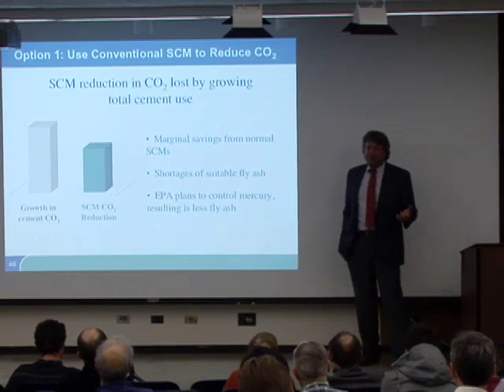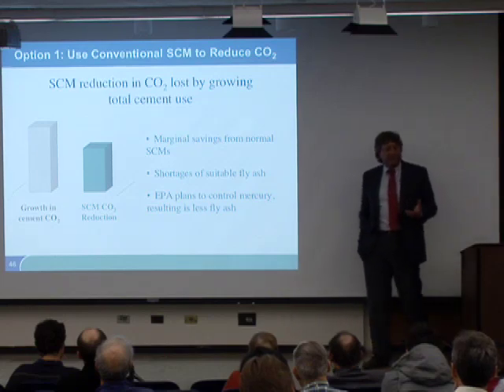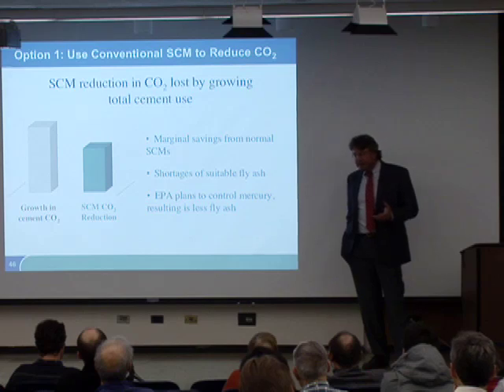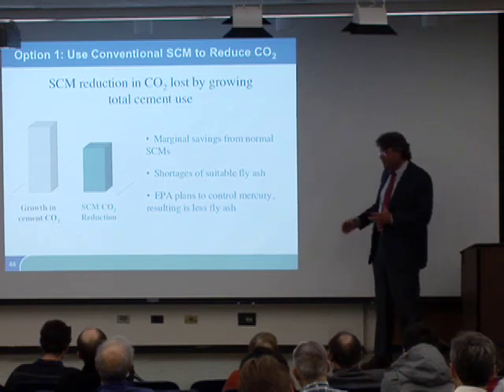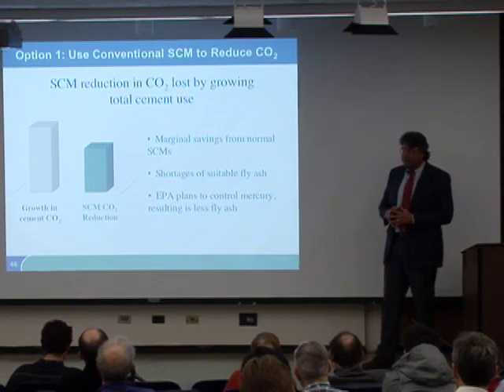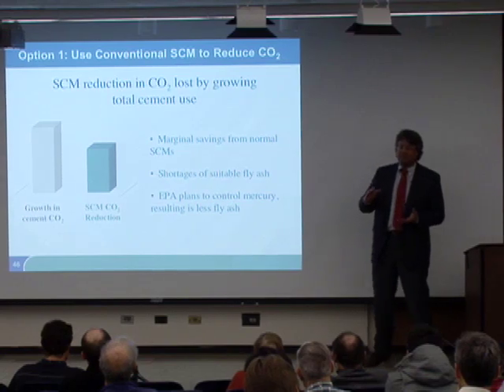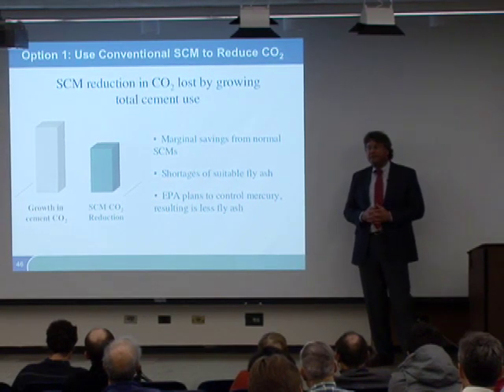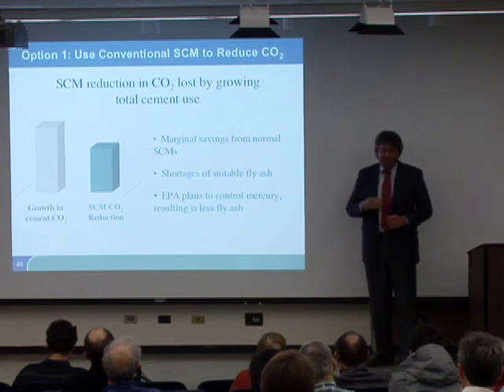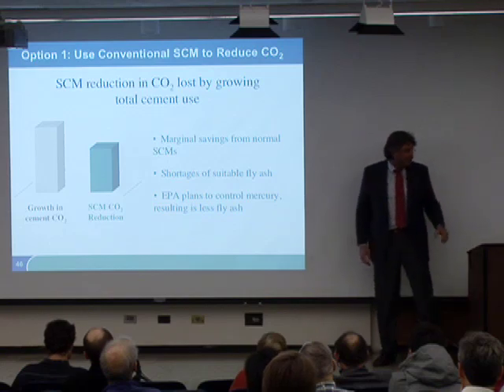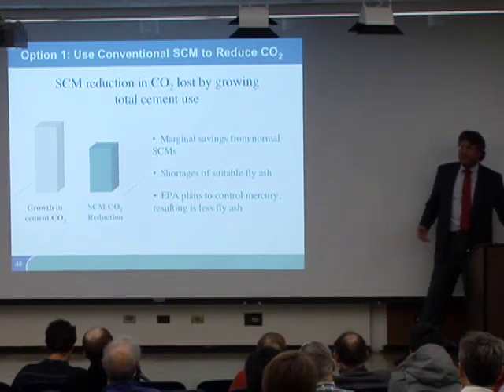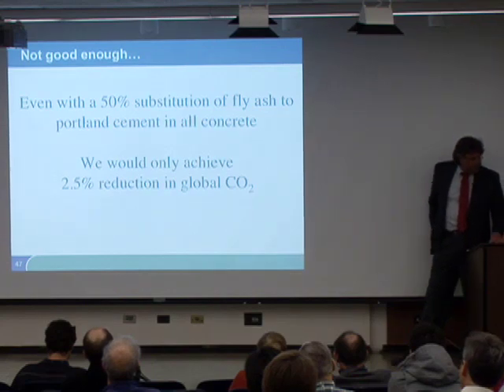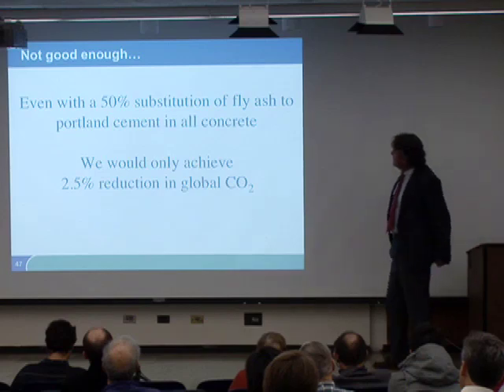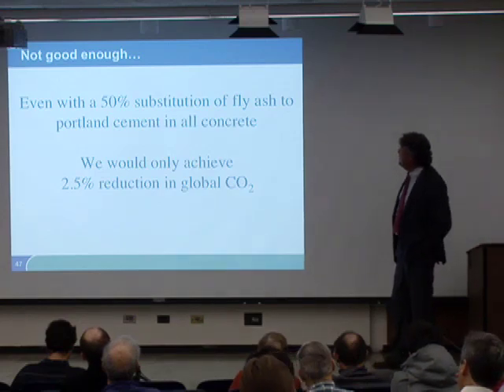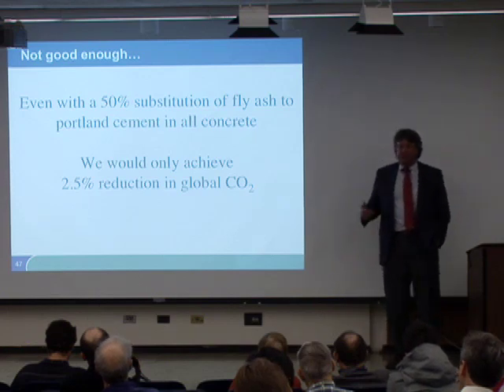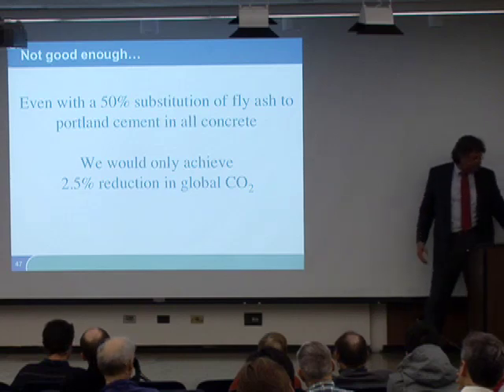There's actually a shortage of fly ash, which is the main one, and blast furnace slag is the other one. The reason there's a shortage of fly ash, well, in the West, isn't because we don't burn coal, but the EPA is coming down on the mercury regulations, and so there's more fly ash which is unusable because it has high carbon in it, which has to do with retaining the mercury. So there's a shortage of these supplementary cementitious materials anyway. But even if we substitute 50% of all the Portland cement with fly ash, that would only result in a 2.5% reduction of CO2 worldwide.